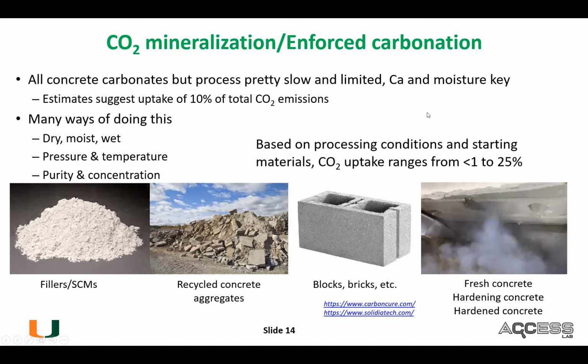But basically, when you do the carbonation, it could be completely dry, you could have a little bit of water, or you could almost do it in a steady state. Pressure and temperature can be greatly varied. The purity and concentration of CO2 can be greatly varied as well. You see anywhere from 1% of CO2 - remember, normal concentration of CO2 is 400 ppm - to anywhere from people using 80, 90% CO2, which is pretty scary.